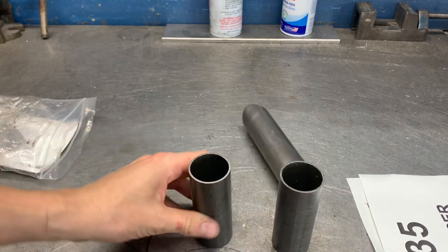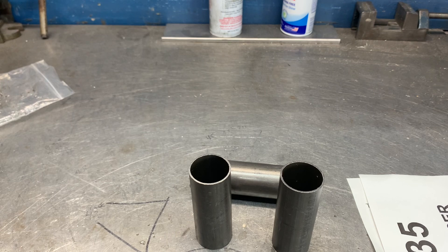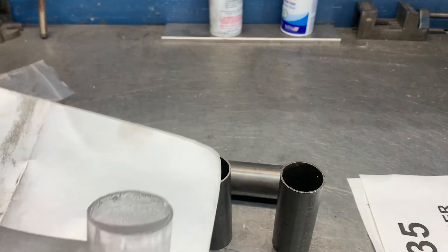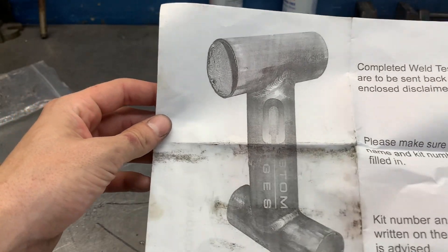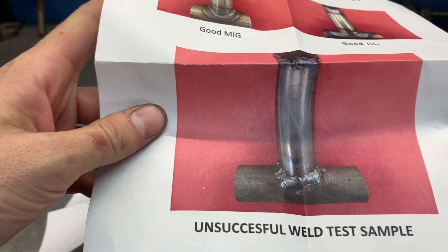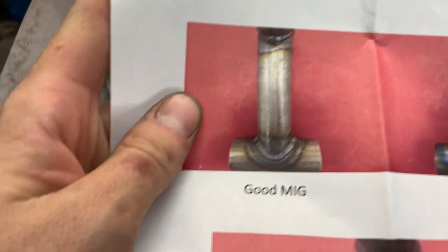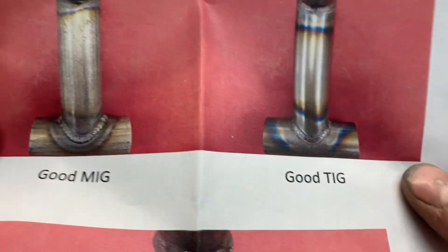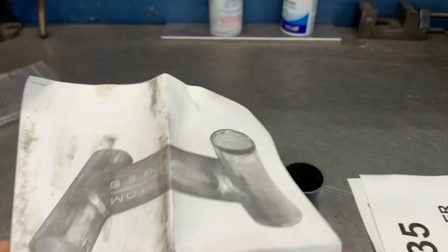First thing first is to get a weld test. You have to do this test and pass it before you weld it in, because if you fail, then your cage won't be certified. I see a lot of cages coming in looking like this — this is not what you want. Even MIG welding with the T45 that it's made out of, you can see how deep the heat affected zone is. Even that TIG weld, they went a little crazy with how hot they got it. Penetration is always going to be better, but you do have to be a little careful — if you get it too hot, it'll get brittle and crack and you won't pass the weld test.